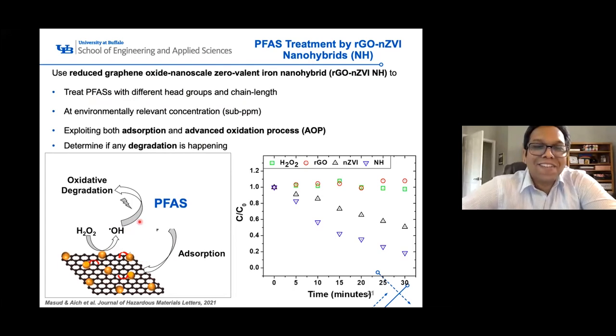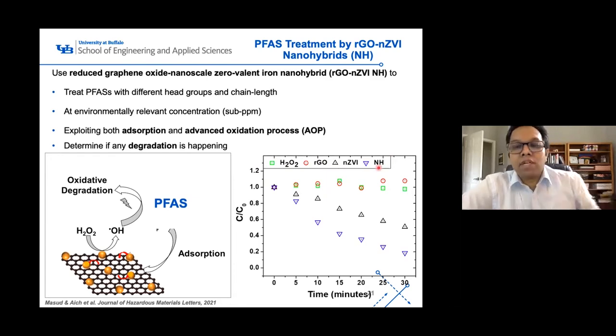No, it's okay. So we are trying to do both adsorption and advanced oxidation process, because only separating them is not going to solve the problem. We need to actually degrade them, okay? So what we try to do to understand if our materials have degradation capability, we looked at hydrogen peroxide decay using different materials. So this is hydrogen peroxide over time that's not decaying, but we put in reduced graphene oxide, NZVI, which is the iron, and this nanohybrid, which is a combination of the reduced graphene oxide and NZVI.